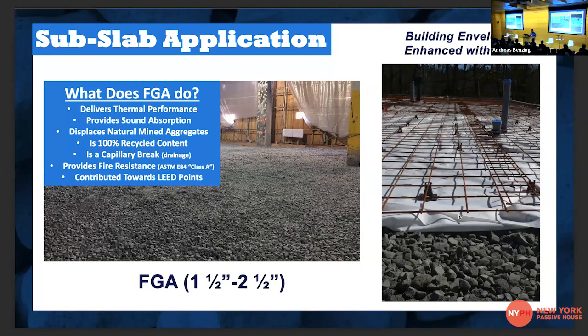Back to the application. It's a capillary break. So instead of using 6 inches of crushed gravel so the water can run laterally underneath the building, stop the hydrostatic pressure pushing up into the slab, the foam glass replaces the natural aggregate, then it replaces the insulation.